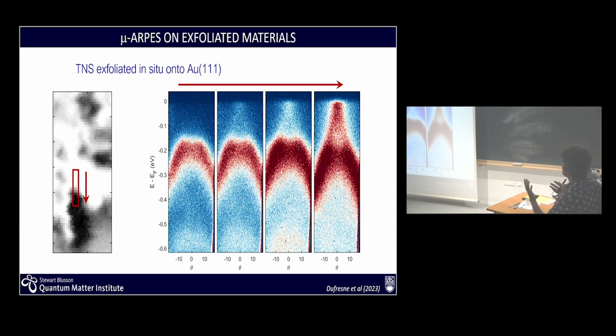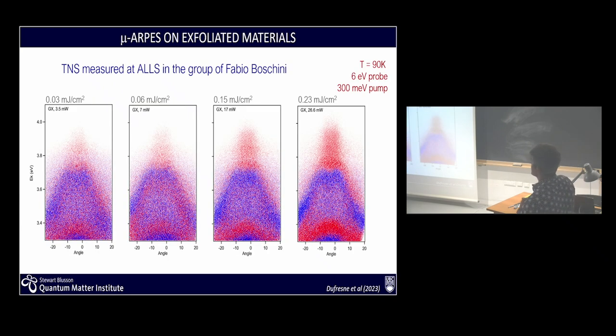So that really suggests very strongly that it's just enough to change the electronic content and the screening in particular to quench that state, suggesting that the nature of this state may be electronic in origin, so potentially an excitonic condensate. Similarly, we have now done a pump and probe experiment, but not on a flake, but on thick crystals, now using a pump photon energy which is resonating with the gap itself, 300 meV, exactly at the gap.